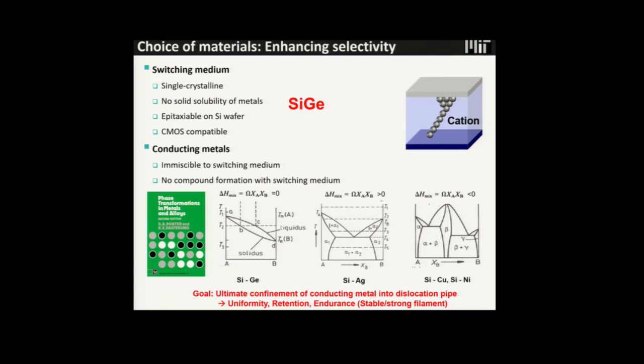Then what kind of metal? Of course, it has to be immiscible to the switching medium. So you can easily find one, because many metals are immiscible to silicon and silicon germanium. And this metal shouldn't make any compound with the switching medium. For example, if this metal forms a silicide with silicon, then there is no more switching, because your metal is already stuck at the sidewall of the dislocation. So you have to do some very basic metallurgical design to do so.